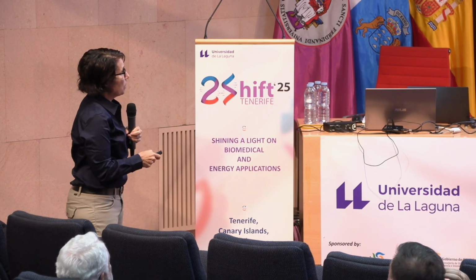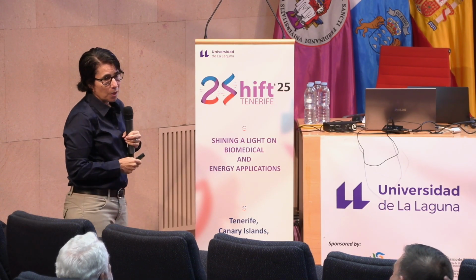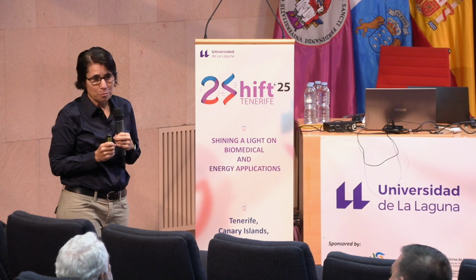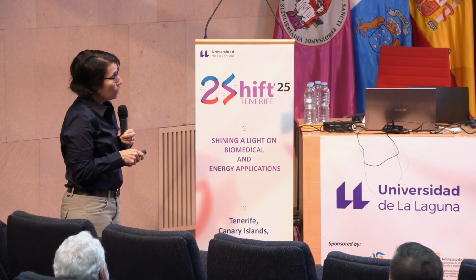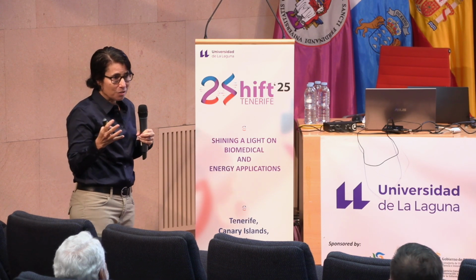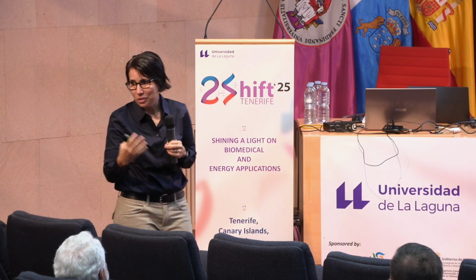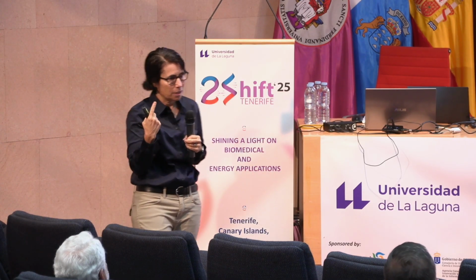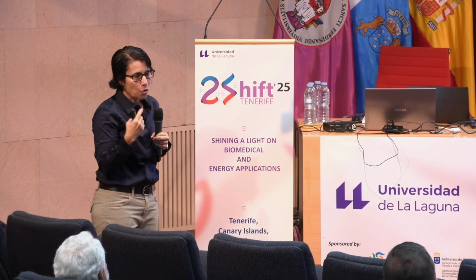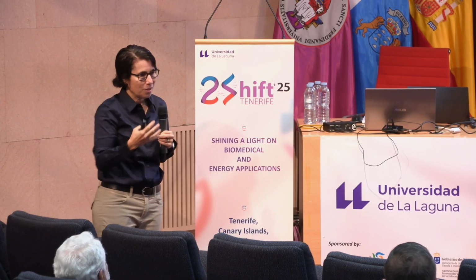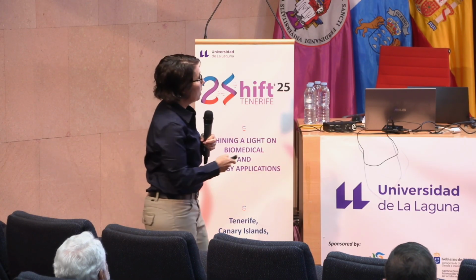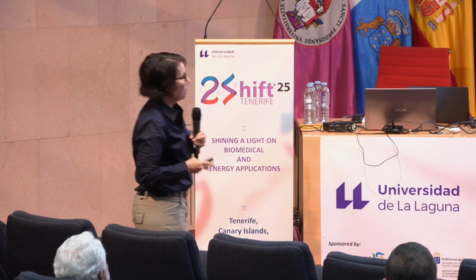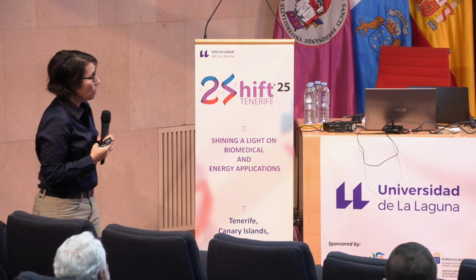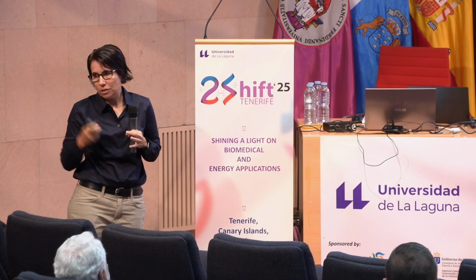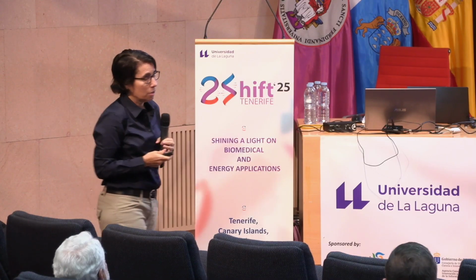And the nice thing about this is we can do this over a large area. The reason for also choosing dielectric metasurfaces is that light from the sun will still come through. This is mostly transparent except for where our resonance is. And that means that we don't disturb the photosynthesis and processes that occur in the leaves, and you can make these on rigid and plastic surfaces. And now these structures have large changes. The magnitude of the reflectivity is large.